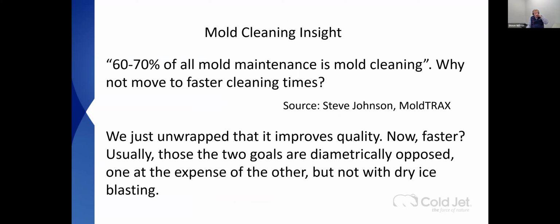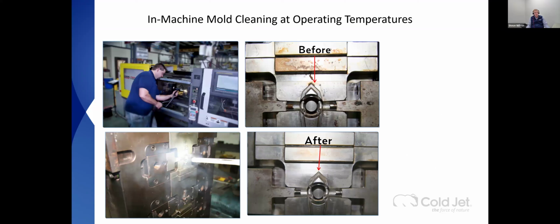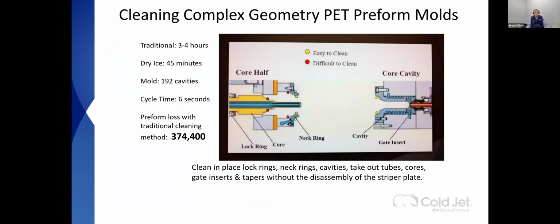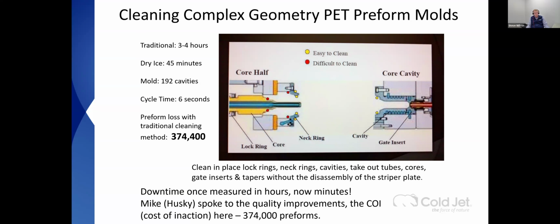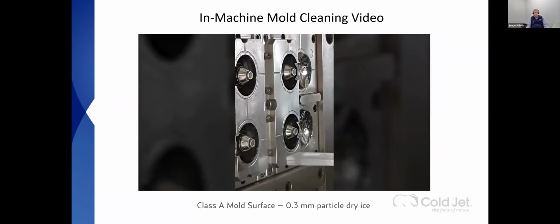We just showed you how to improve quality. And usually when you go faster, you sacrifice quality. It's not true with dry ice. You're going to go out to the machine, open the gate, clean the cavities and vents, and I can get you down to an area, a very small micro molding, give me about 1.5 inches, 2 inches, I can get you clean. This is the guy that went from 3 to 4 hours down to 45 minutes. Every time he had a shutdown before, they were losing 374,400 preforms. Much faster. Downtime was measured in hours, now minutes.